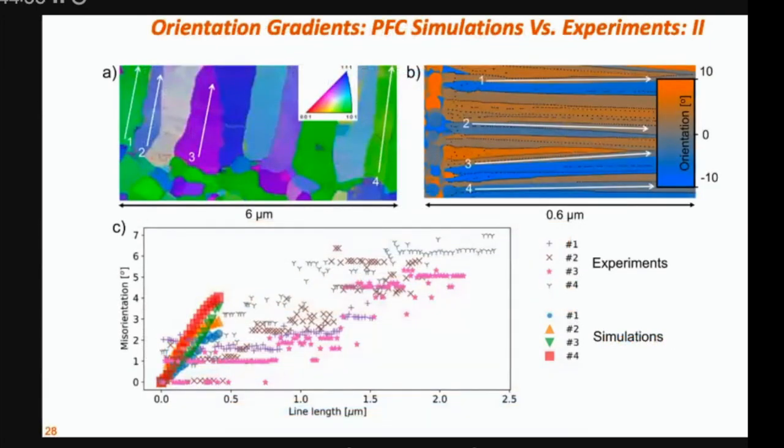What I draw your attention to at the top one here is notice all the blue area is one crystal, one orientation. But notice that it gradually changes orientations within a crystal. Same thing here. You get the variations in hue within a single crystal. And notice there's a lot of these dots lying around. These are defects I'll talk about right now that are presumably mediated or responsible for this orientation change being allowed during crystallization.